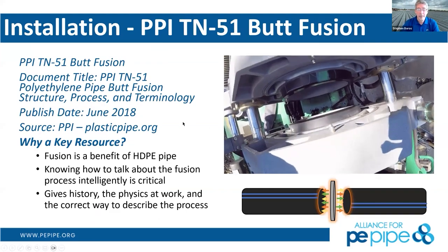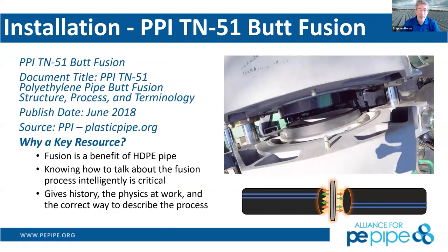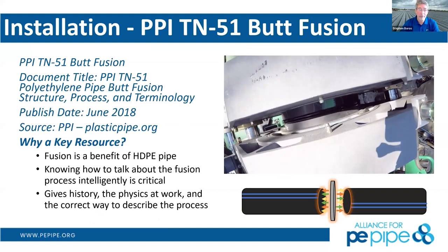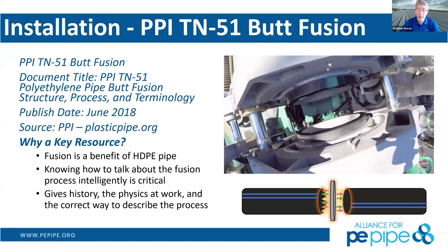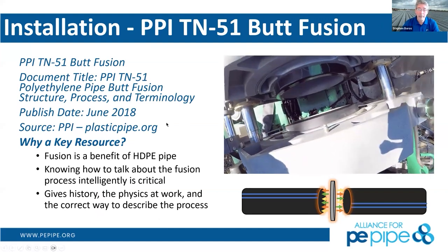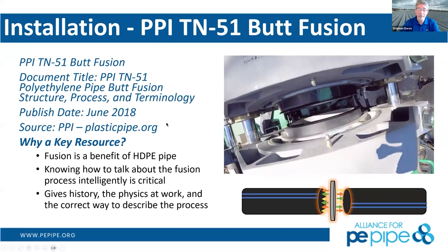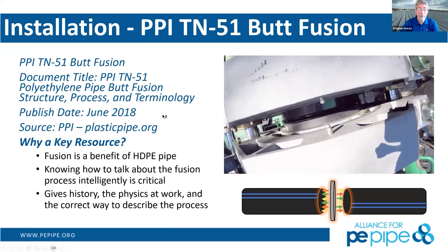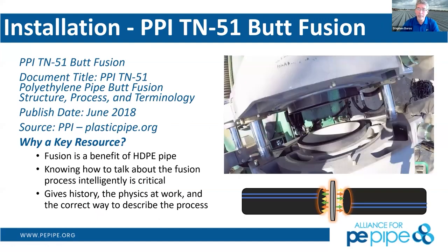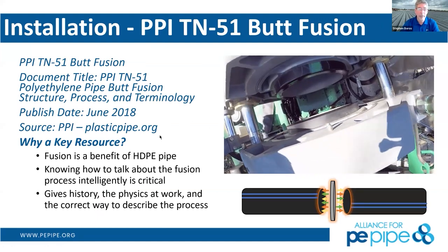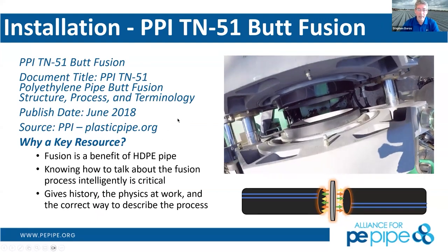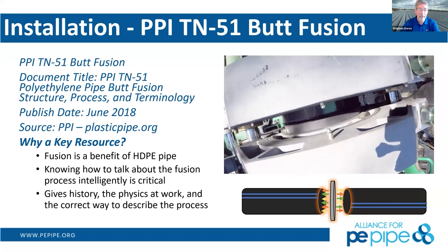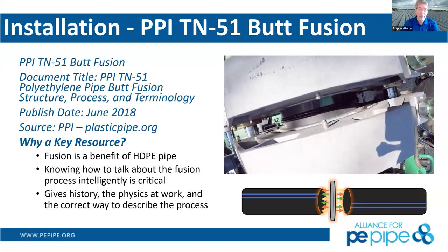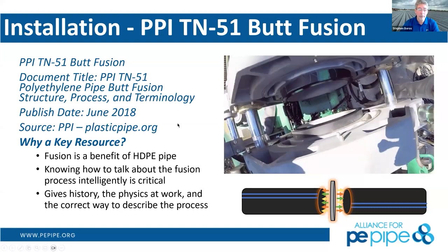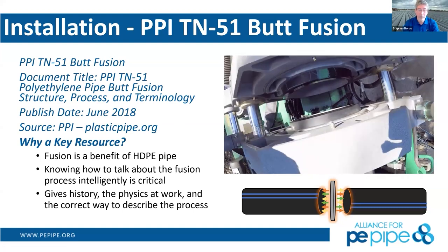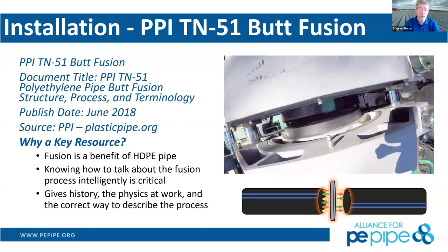TN51 talks about butt fusion. Butt fusion is the number one heat fusion joining method for polyethylene. It doesn't require a fitting. It requires a fusion machine to align the pipe and bring it together in the right fashion. But once it's brought together and it's fused in this manner, it becomes a monolithic pipe piece at that point. There's no longer a joint that's going to come apart. Again, that joint is now as strong as the pipe. It's fully restrained, and it won't ever be a weak link that's going to be a problem within your piping system. So that's the number one way of doing it.